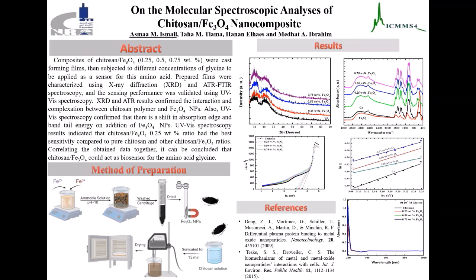The magnetic nanomaterials are mainly prepared from two major aqueous solutions, which are ferrous and ferric, as clarified in the preparation scheme. As observed, FTIR and XRD confirmed the complexation and interaction between chitosan and iron oxide. Also, the band gap energy and absorption edge changed on the addition of iron oxide to chitosan, which indicated a high density of localized tail states in the chitosan iron oxide nanocomposite.